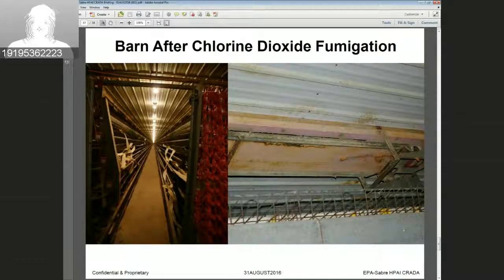We've done a lot of material compatibility studies looking at the impact of chlorine dioxide. It will oxidize all mild steels, and it will start to attack some of the stainless steels. That's what you have to be careful of, especially the newer generation of barns. These did not have elaborate control systems. They had several California barns adjacent to these that they showed us, and that would be one of my concerns with fumigation of chlorine dioxide of these barns: assessment before and after of the control systems inside these barns, because the chlorine dioxide will have a tendency to attack those. But in these barns, we did not see any material impacts that were not already there.